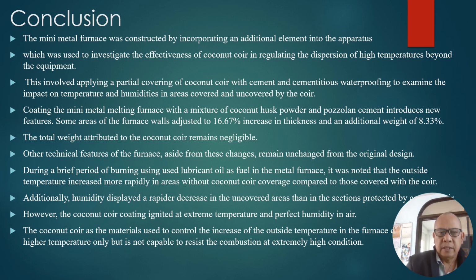a 16.67% increase in thickness and an additional weight of 8.33%. The total weight attributed to the coconut coir remains negligible. Other technical features of the furnace aside from these changes remain unchanged from the original design. During a brief period of burning, using used lubricant oil as fuel in the metal furnace, it was noted that the outside temperature increased more rapidly in areas without coconut coir coverage compared to those covered with the coir. Additionally, humidity displayed a more rapid decrease in the uncovered areas than the sections protected by the coir. However, the coconut coir coating ignited at extreme temperature and perfect humidity in the air.